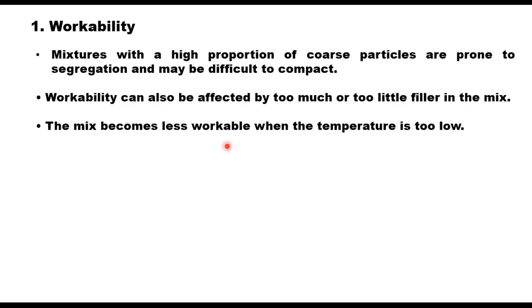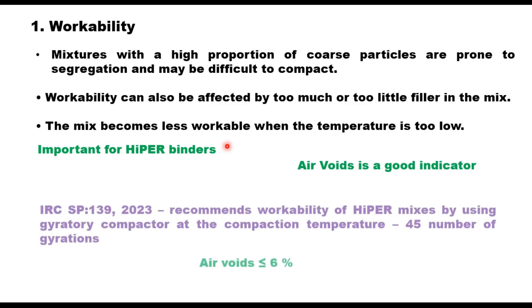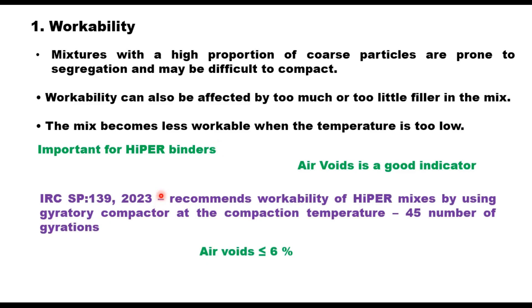The mix becomes less workable when the temperature is too low. Workability is important for high performance binders because their binder viscosity is quite high. Air voids can be a good indicator to determine workability. IRC SP 139:2023, which deals with high performance binders and mixes, recommends assessing workability using a gyratory compactor at the compaction temperature. After 45 gyrations, air voids in the mix should be less than or equal to 6%.